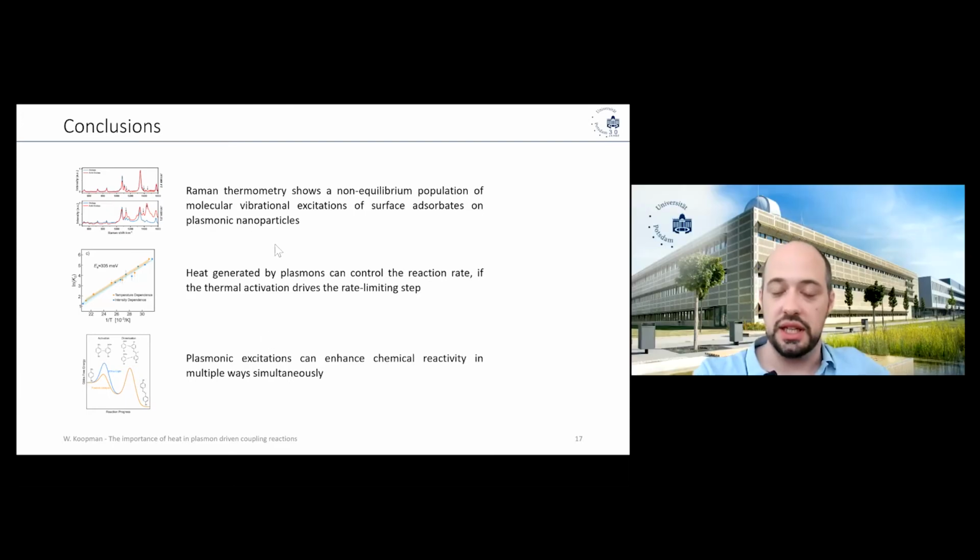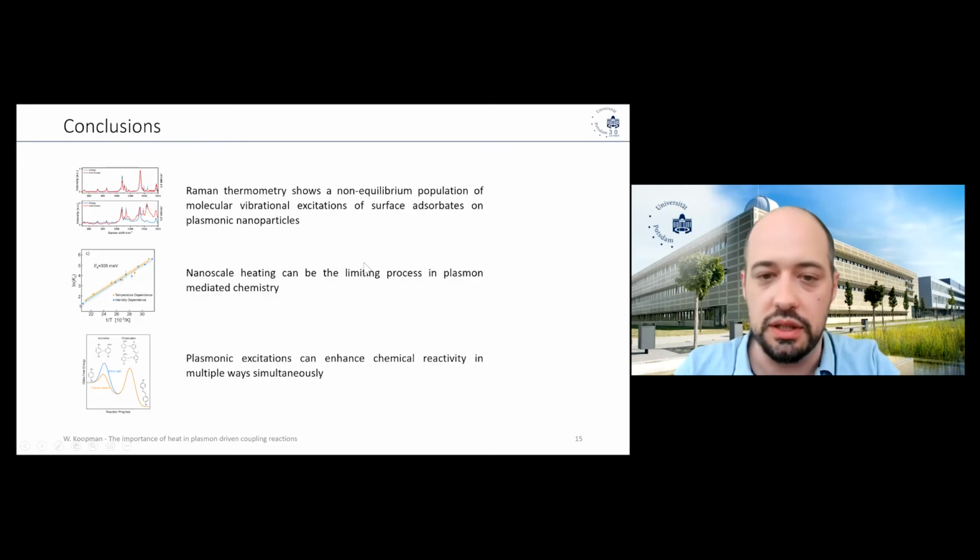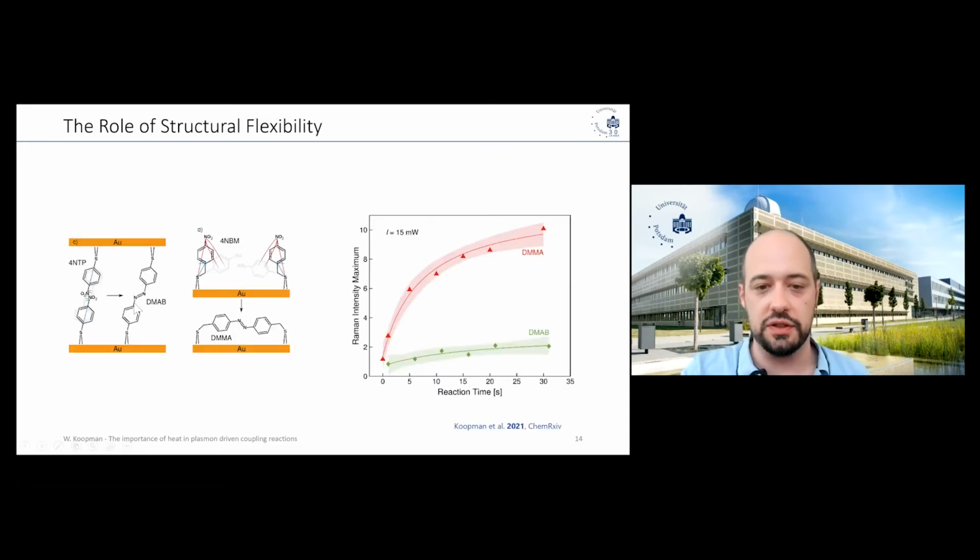How it geometrically is possible that the dimers are formed, that's actually not entirely clear. Because if we compare the DFT calculated Raman spectra of the dimer to what we measure experimentally, then we see that it's probably indeed this kind of cis state. So it has to be bonded in this way.